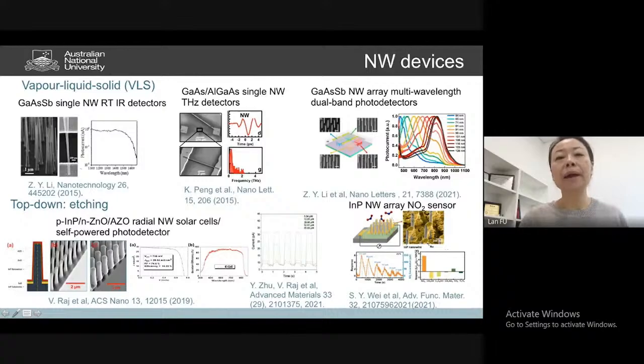And if we're actually making some gallium arsenide, aluminum gallium arsenide single nanowire, we can make them as a photoconductive terahertz detector, to detect some really narrow terahertz response because of the fast nature, due to the large surface area of the material, and the fast carrier decay response can be achieved. So we can actually make them as a photoconductive terahertz detector.